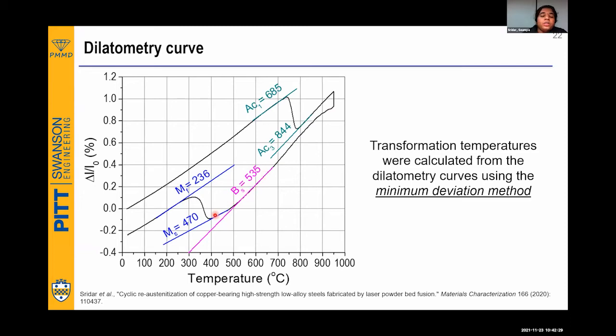And then you see this obvious change, which corresponds to the start of the martensite, which is the MS temperature, and this corresponds to the finish of the martensite transformation, which is the MF temperature. And again, it goes back to room temperature.